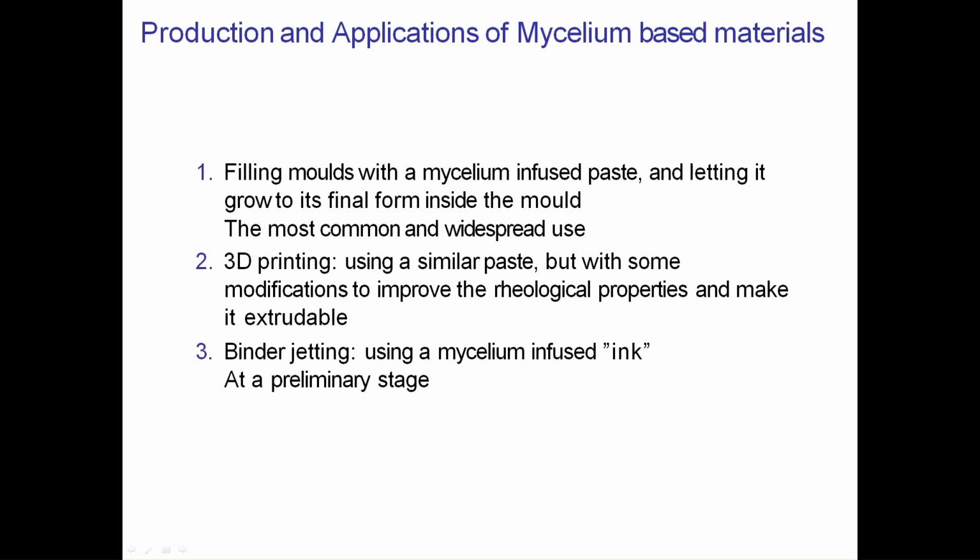The dominant production method of mycelium-based composites is molding. Molds are filled with a mycelium-infused paste, letting it grow until it reaches its final form. 3D printing is a more recent take on mycelium-based composites production. It uses a similar paste, but with slight modifications to make it extrudable. The paste is used as the printing material, and the mycelium reaches its final form after the print.